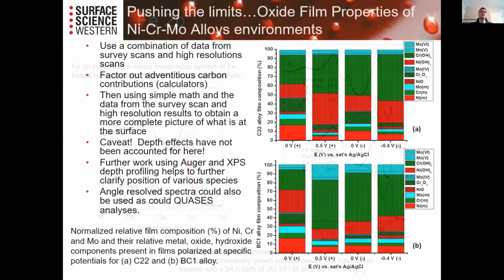And so if you take that kind of curve fitting and combine it with other information that you have about the sample, so in this case, we take the curve fitting of nickel, chromium, and molybdenum to get at the chemical species that are present, combine that with the data that we're getting from the survey scans, we can then, with simple math, pull out what's going on at these surfaces? And you can say, okay, here we have this much metal, these are different metals, and these are all the different oxides present.